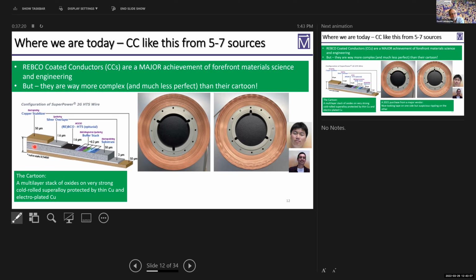And so what you have is a very strong cold worked superalloy substrate, a nickel base alloy, Hastelloy. And this has to be rolled to a very, very smooth thing. It's then electropolished. You then put a solution of oxide onto the surface to utterly smooth it. You then come along and you deposit magnesium reactively in an oxygen environment, so it produces magnesium oxide as it goes down. And at the same time, you hit it with an ion beam. And the ion beam, at a very well-defined angle, produces the almost instantaneous texture in the MgO that is manufactured. So with less than 50 nanometers of MgO here, you have a perfect 100 texture. But it's very, very thin, so you grow it homoepitaxially, perhaps to double that thickness.